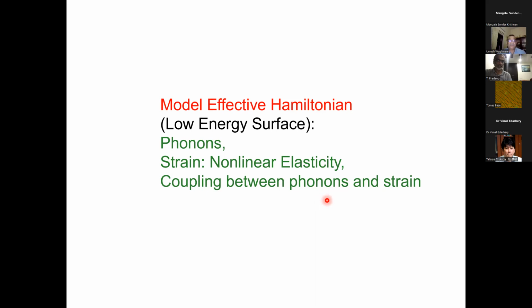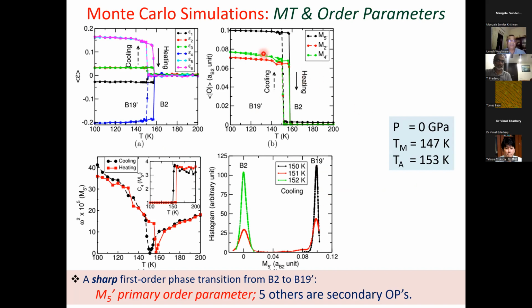And then using this model Hamiltonian in Monte Carlo simulations, we can predict phase transition behavior of these systems. And you will see, unlike barium titanate, these phase transitions are quite sharp. At the transition temperature, the strain, these are basically the a, b, c lattice parameters, change suddenly at the phase transition, and there's a hysteresis which reflects the first order character of this phase transition. And this is the M5 prime phonon, the cell doubling phonon. It also discontinuously switches to its low temperature phase.